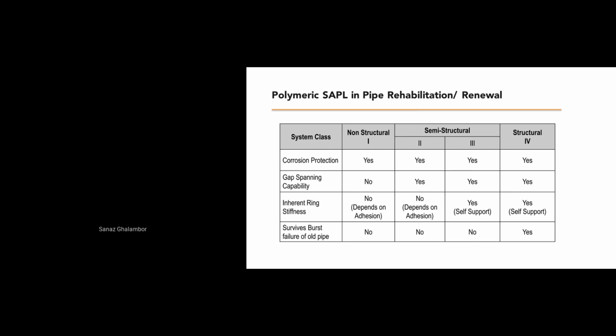If the pipe is in good shape, if it can carry the live load and dead load, but it has some leakage or pinholes or cracks, we can use this technology for semi-structural pipe rehabilitation to prevent ingress and egress of water. And in cases where the pipe is very old, has lost its structural integrity, and is not in good shape, we can apply the system to renew the pipe, to make a new polymeric pipe inside the pipe so that it can extend the lifetime of the pipe for another 50 years minimum. So this system can be used in different classes from non-structural to full structural, depending on the condition of the pipe and project specifications.